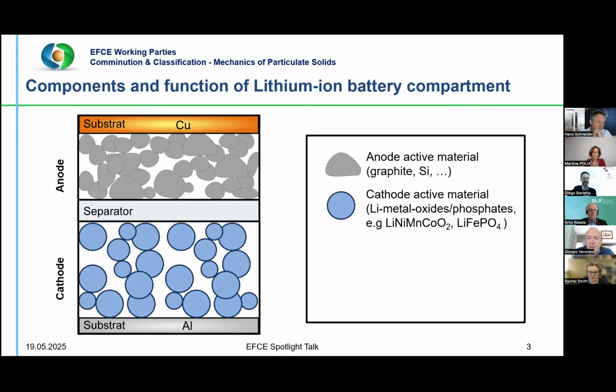Let's have a look at the structure of the battery compartment and its main components. The primary anode material is graphite, typically with a particle size around 20 microns, exhibiting a layered structure that facilitates lithium-ion intercalation. Silicon, with nanoscale particle forms below 150 nanometers, is explored as a high-capacity alternative.